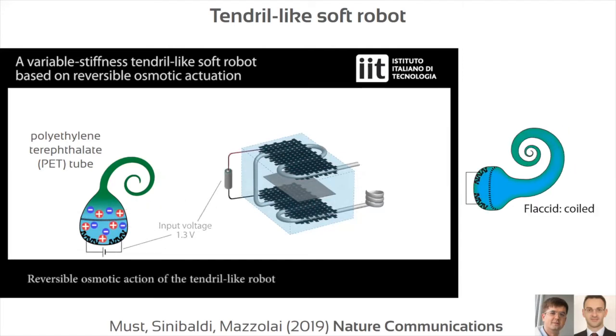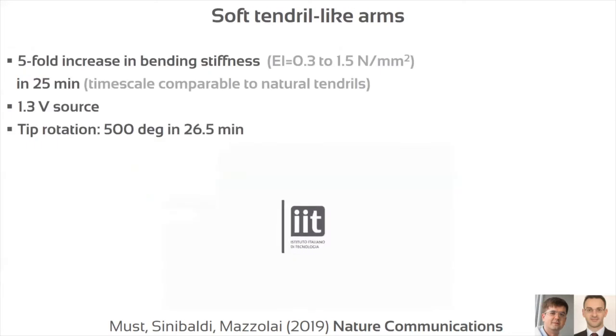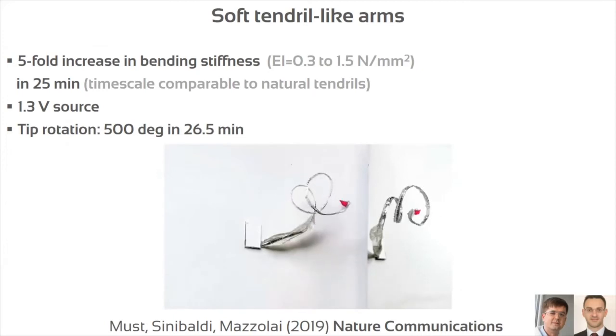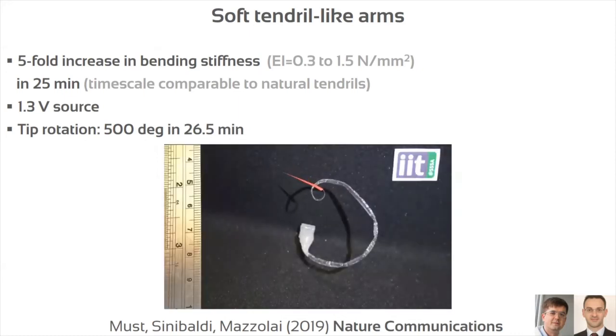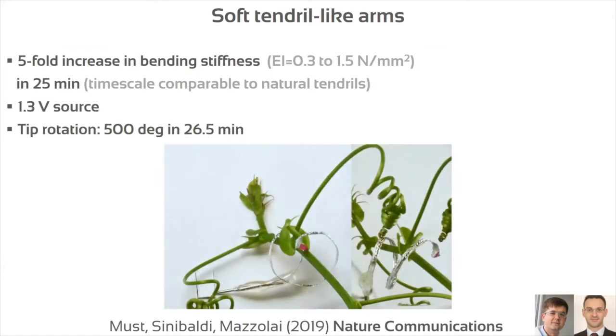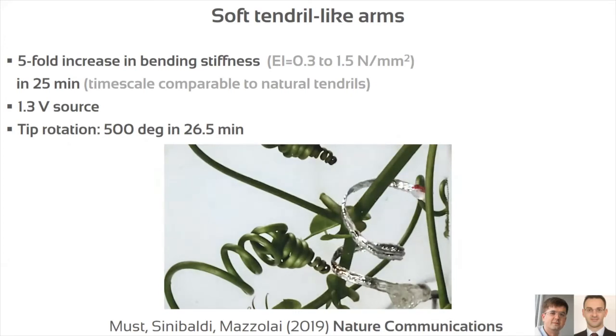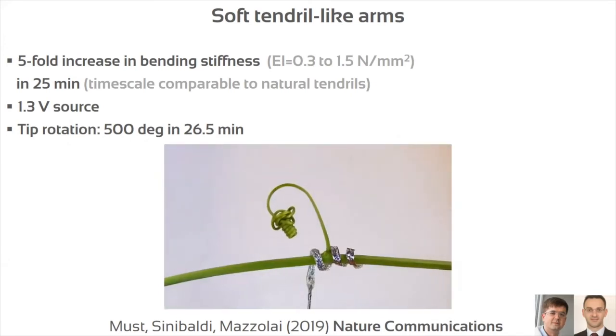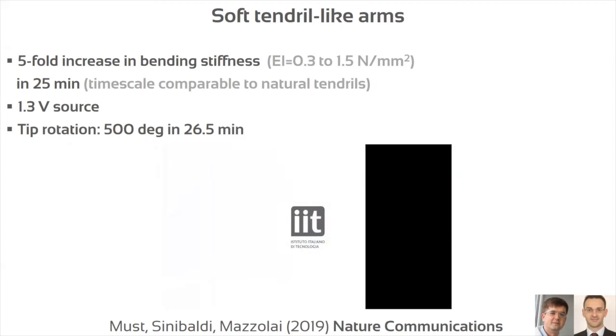So what we obtained is a soft robot that can completely coil and uncoil around the support. We apply 1.3 volts, so it's quite a low source, to generate this absorption and desorption of ions, as I mentioned. And what we can obtain in around 25 minutes is the coiling and uncoiling of the system. So the system is completely reversible, and during the movement of water, as I mentioned, we can increase the stiffness.